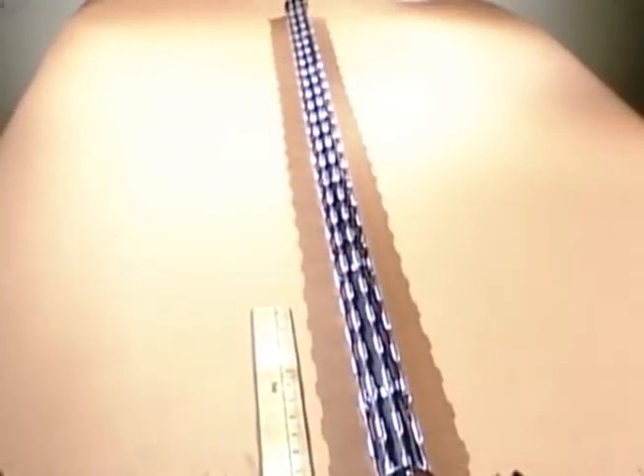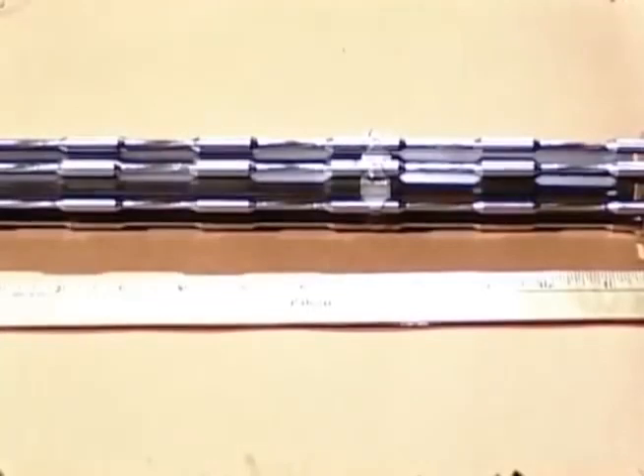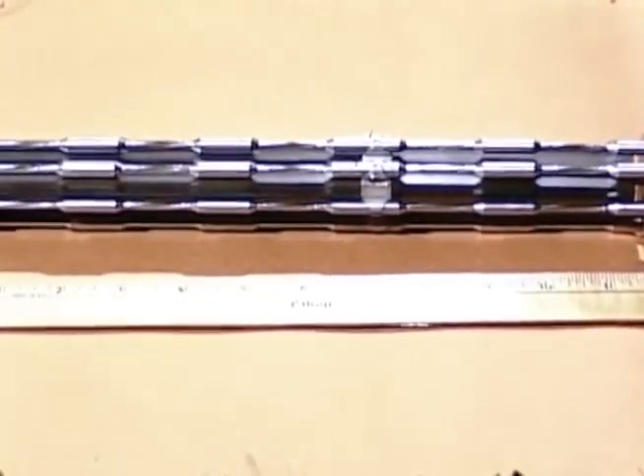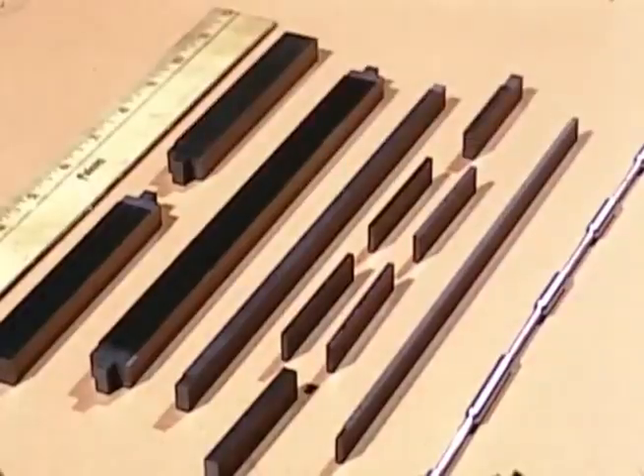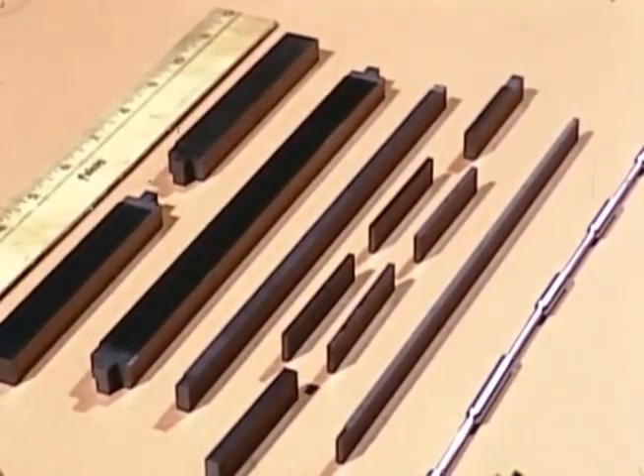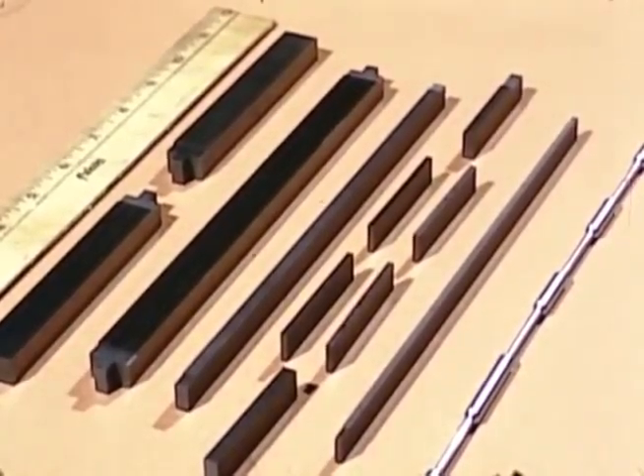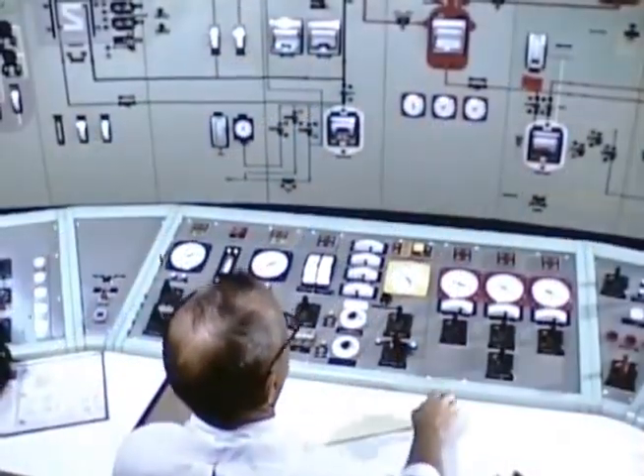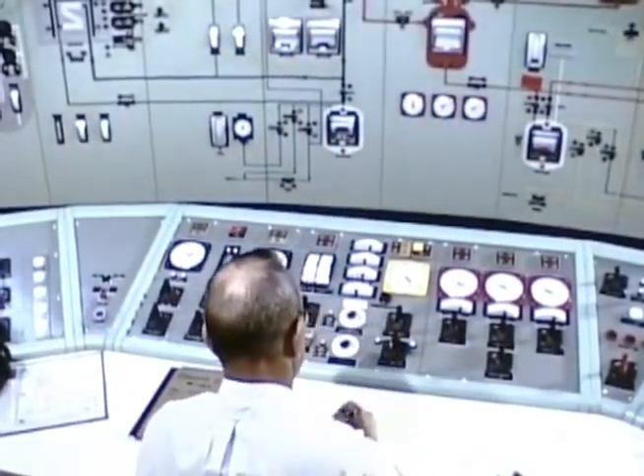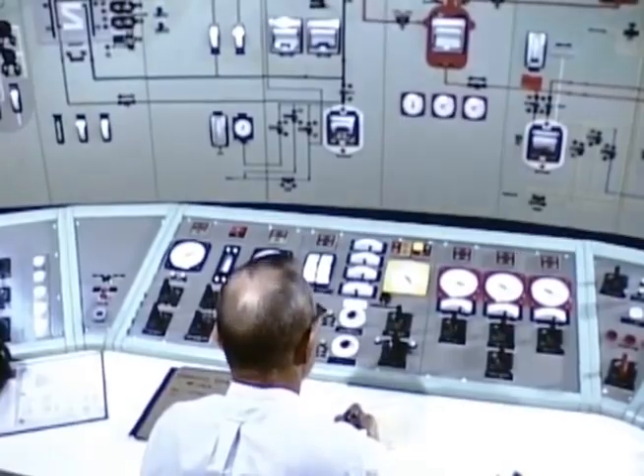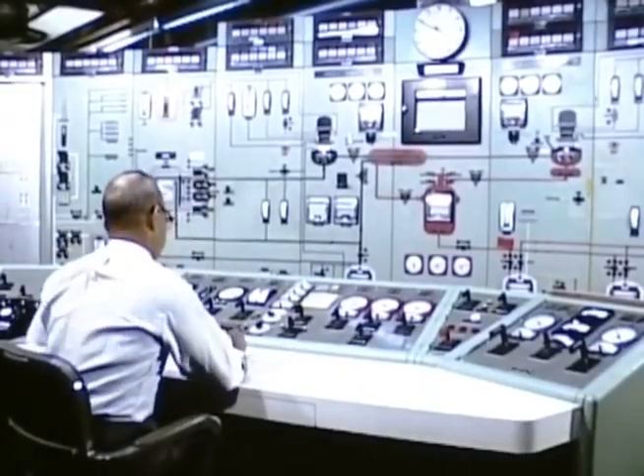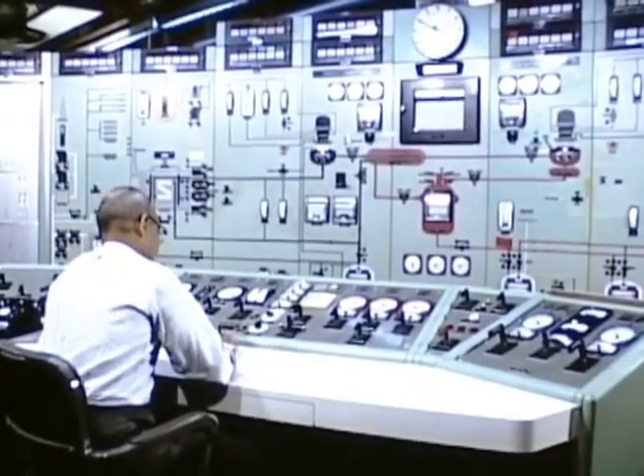Graphite and Hastelloy N specimens similar to these have been removed from the fissioning fuel stream in the reactor core. Examination of specimens in hot cells indicated no deleterious corrosion or structural change after salt had been circulated in the fuel system for more than 6,000 hours. In that time, the fuel proved to be stable to radiation and heat. The reactor, with its 1200 degree core outlet temperature, is one of the highest temperature reactors operating today.